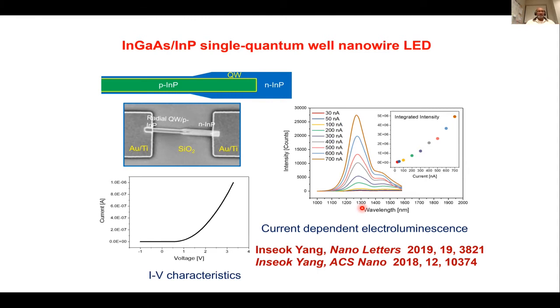It turns out, whenever you put metals on the nanowires, these metals have got large optical losses. If you create a large loss in the cavity, you have to pump them harder to get over the losses. And then if you're pumping harder, you generate a lot of heat, which reduces the gain peak of the gain medium, and in the process it becomes like a vicious circle.